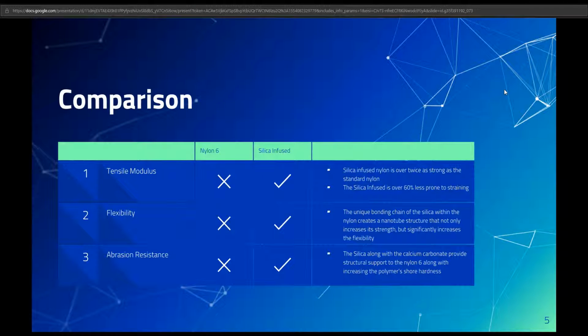A comparison against nylon 6 and the silica infused nylon 6. The silica infused is twice as strong and is 60% less prone to straining. Flexibility-wise, the bonding chains that the silica provide to the nanotube structures increase the strength but also significantly increase flexibility. Abrasion resistance was won by the silica-infused nylon. The polymer's shore hardness was much greater.